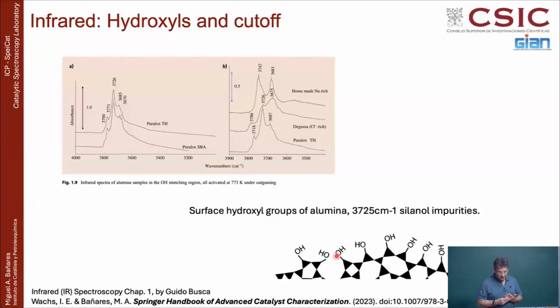And this termination actually has properties. Not all the hydroxyls are alike. Depending on their position, you can already tell whether they are more or less acidic. And also you can tell which kind of cation you are binding to. Like here, for instance, this is just a concept for alumina. Here you have the hydroxyl for alumina, but this is alumina with a little bit of sodium, with a little bit of silica on the surface. So you get the alumina infrared hydroxyl groups, but also some silanol, which is hydroxyls on silica. So they are different. So you can tell whether these hydroxyls are on silica or alumina or on different kinds of elements.